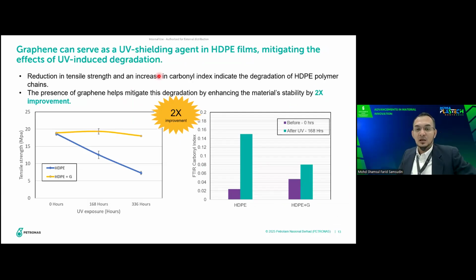And this is another study that we want to highlight here, where we use graphene to study how it affects the UV stability of the HDPE film. We put this film that we blend with graphene at 0.01 weight% in the QUV chamber, and then we monitor for 2 weeks, and we study the mechanical performance and also the carbonyl index. And from here, we can observe that without graphene particle, we can see the reduction in tensile strength from 17 to 7 megapascal. But for the one where we add graphene at 0.01 weight%, it is quite stable, up to 336 hours of UV, more than 2 weeks.